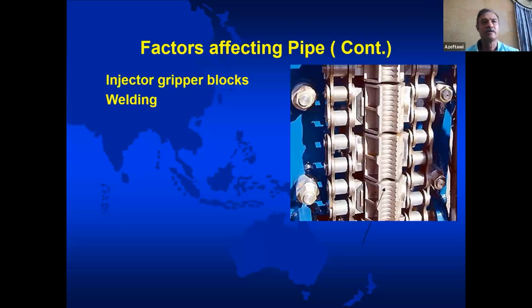But anyhow, without going into details, because this is not the course to talk about that, during the job, you might get a pinhole in the pipe. This pipe you are using has a pinhole. So this area is damaged. So when you go to the yard with your reel, you need to take this damaged part out. So you cut it out, then you weld it together again. When you weld the pipe together again, you weld it using a butt weld, which is a weak point.